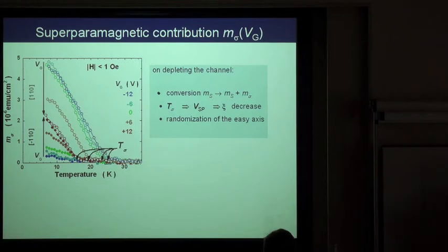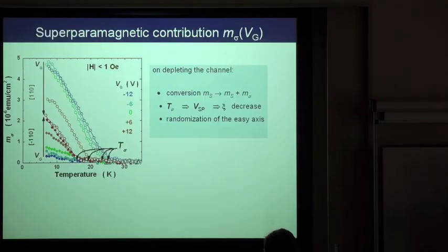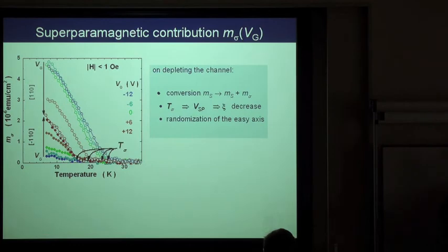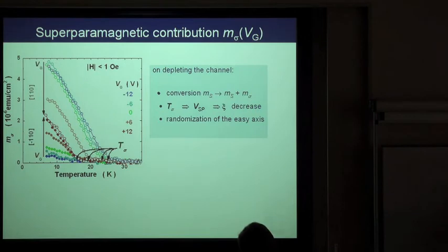In the ferromagnetic case, we have a very well-defined easy axis; the material becomes more superparamagnetic, less so. So what would be the conclusion from what I said here? That in the transition from ferromagnet to paramagnet, without holes we have a paramagnet, with a lot of holes we have a ferromagnet, but in between we go through superparamagnetic phases. Locally we have ferromagnetic order over there. So the question of how ferromagnetism disappears is a question of how the system looks locally. It's not that we have a homogeneous ferromagnet and jump to a homogeneous paramagnet; we go through a kind of superparamagnetic phase of all this.